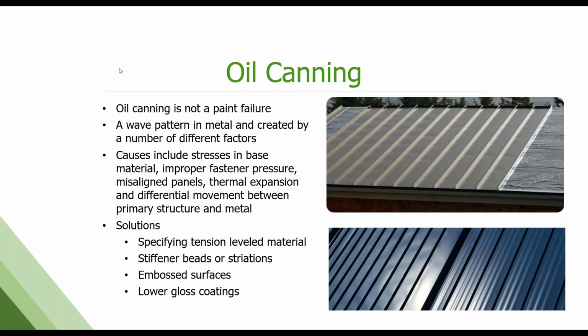Oil canning. It's not a paint failure, but it is something that light gauge steel is prone to, especially in flat profiles. You get that wave or buckling in the panel. It can be caused by stresses in the base material. It can be improper fastener pressure and location. It can be misaligned panels. It can just be normal thermal expansion and differential movement between the structure and the metal panels themselves. The way to avoid this, make sure you're getting tension leveled material. Add stiffener beads or striations. If you're doing long length, anything above like 10, 12 foot spans of panels, probably want to put some striations, can emboss the surface. Low gloss coatings actually minimize this look too. It's still there, you just don't see it as readily.